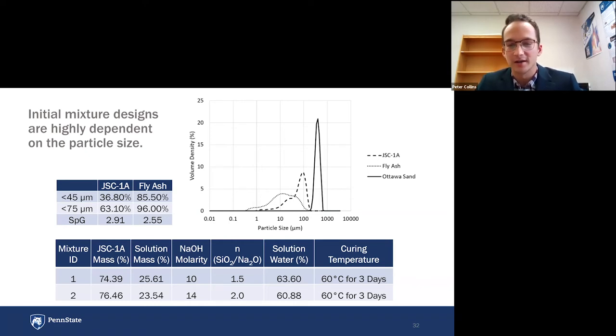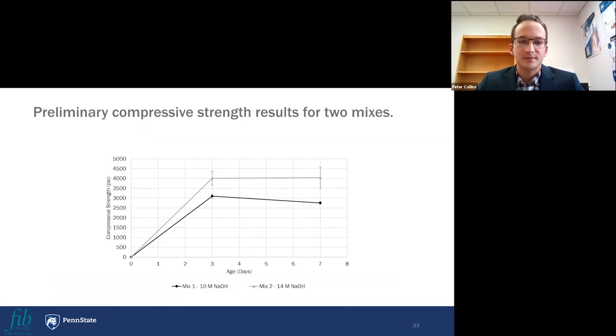So we're trying curing temperatures right now. 60 degrees Celsius is common for geopolymers, and then we will work our way up also to the lunar temperatures of like 110 degrees Celsius. As far as some preliminary compressive strength results go, I've got some 3-day and 7-day strength results I'll share with you.